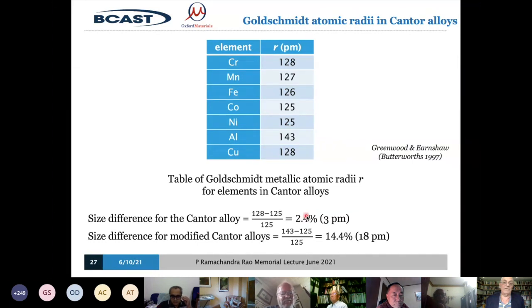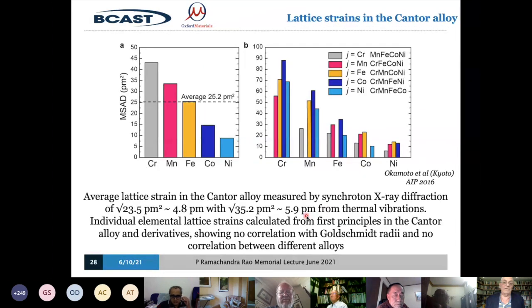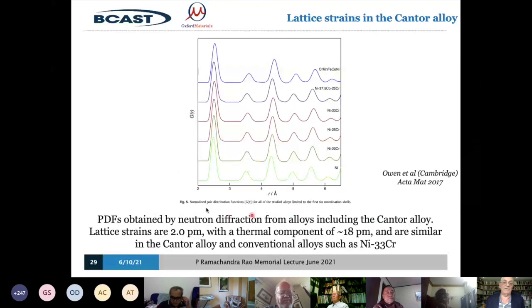Well, it's quite hard to measure those local deviations, but synchrotron X-ray diffraction gives an answer of 4.8 picometers, and neutron diffraction gives an answer of 2 picometers. So it's about right. It's in the 2 to 5 picometer range, which is in the 1 to 5% strain range. Small sounding as it is, it's actually a lot in terms of the straining of a material.